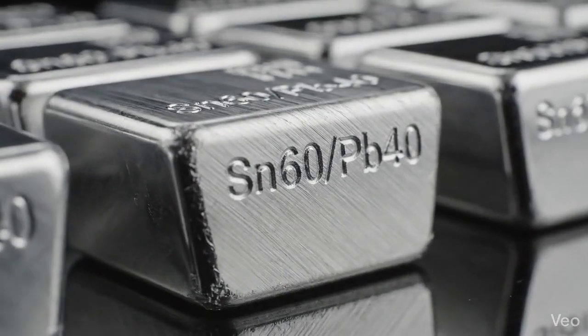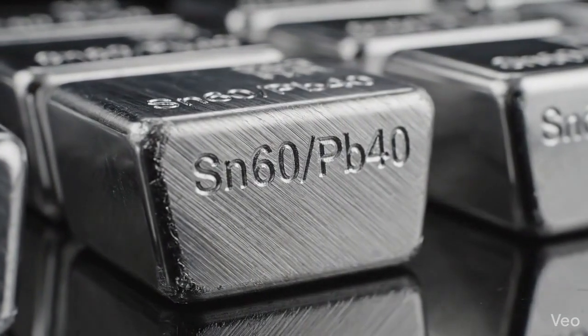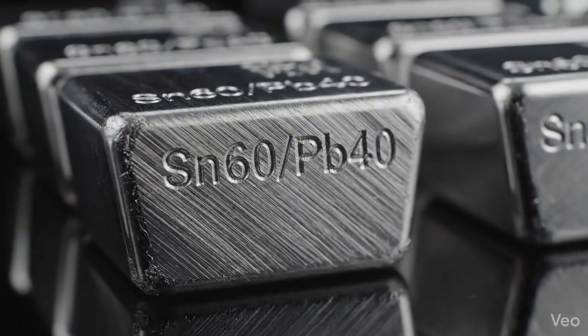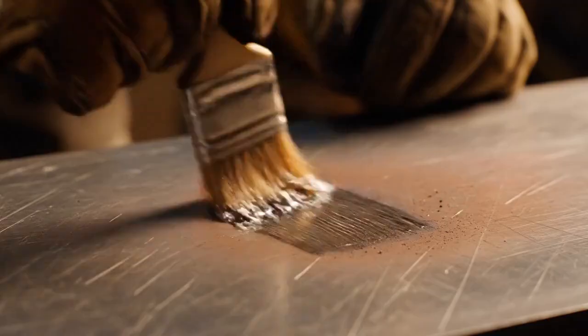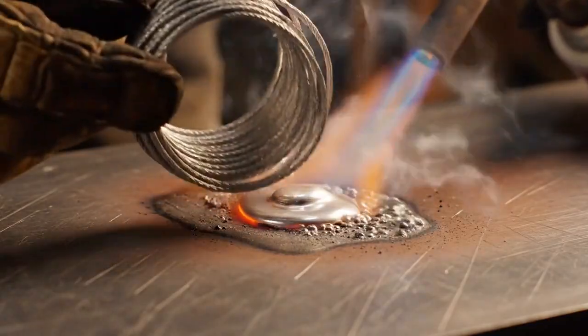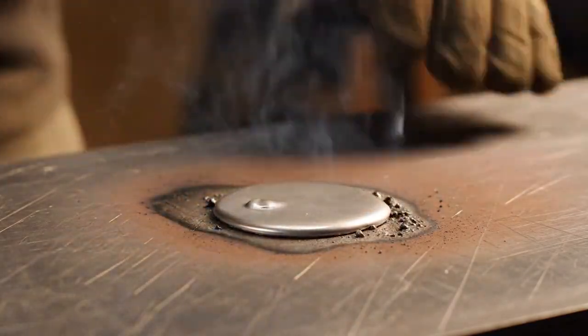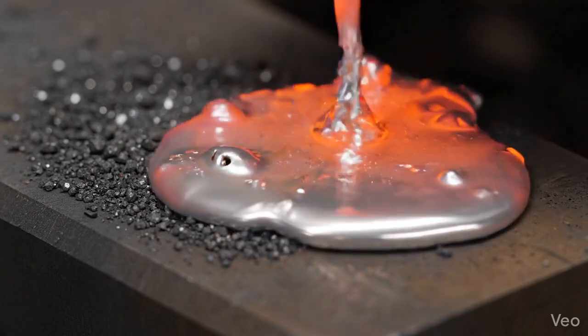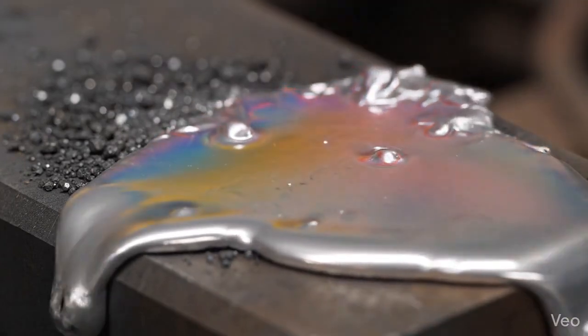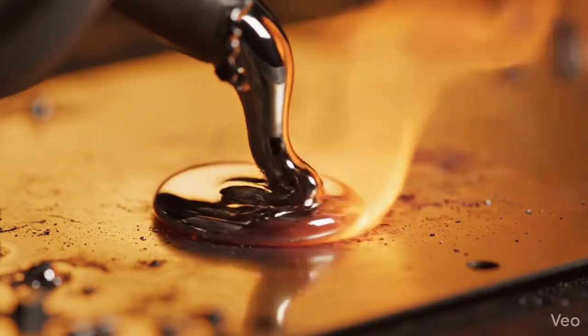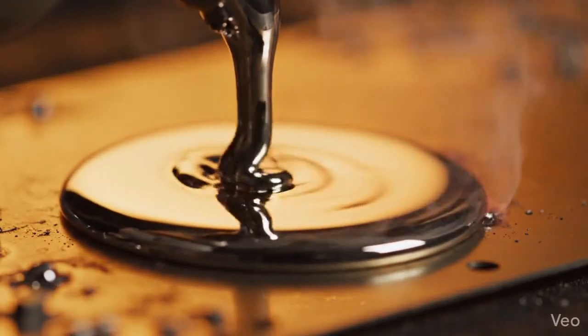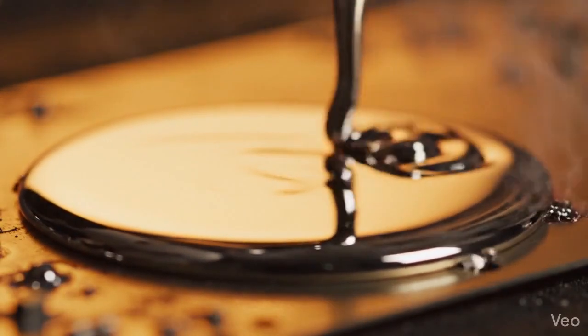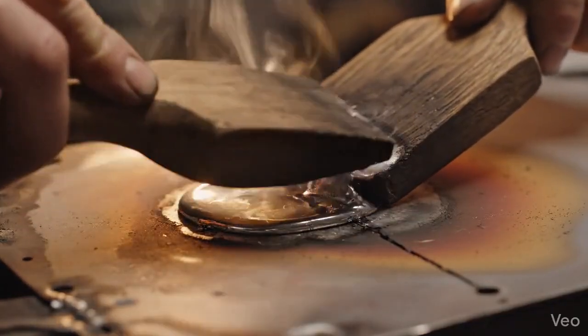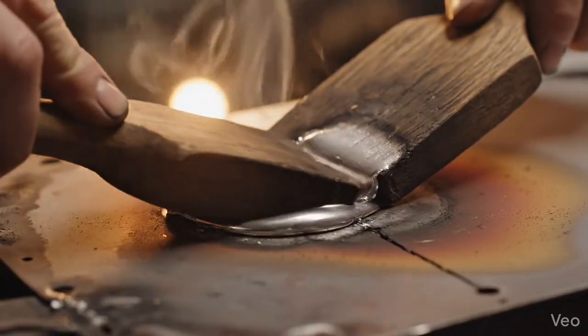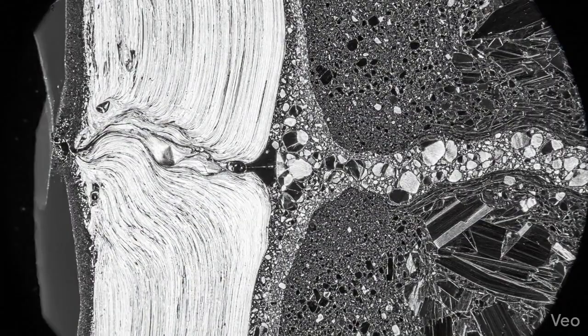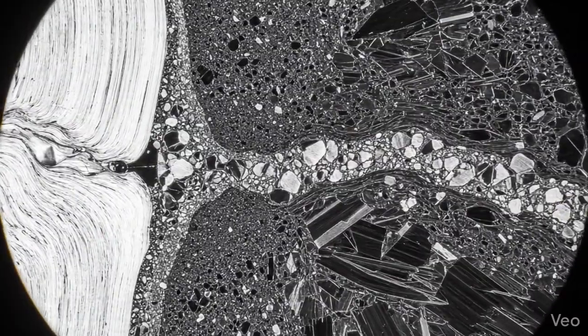Lead tin solder, typically in a 60-40 or 40-60 ratio of tin to lead by weight, behaves differently because of how it is applied. The steel is tinned first. A thin coating of flux and metallic tin is worked into the prepared surface with heat and a brush, creating a chemically receptive layer bonded to the steel. The lead tin rod is then applied to the heated panel, flowing into the tinned area and shaped smooth with a forming paddle while still soft. At application temperature, the solder fuses with the tin layer and through it into the steel itself. The bond is not adhesive, it is metallurgical.